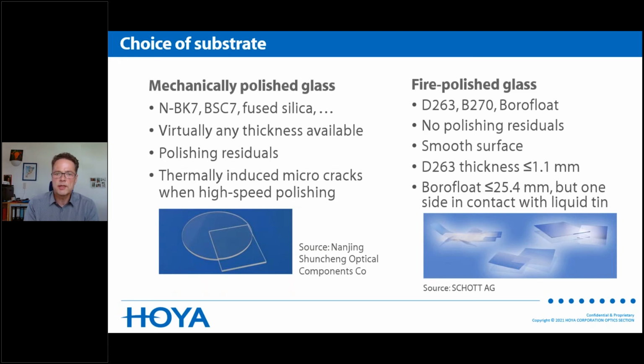And as I explained, these modern coatings, the thicker they become, the more stress they induce. So people are looking for alternatives, which could be borofloat, which you can get at 1 inch maximum. But you have to consider that due to the production process as a float glass, one side of the substrate is in contact with liquid tin. And again, polishing might be necessary to remove that tin.